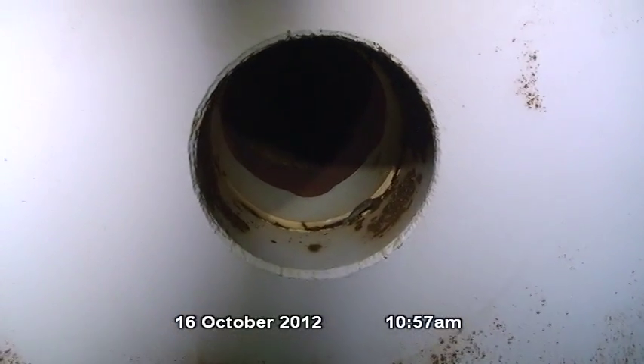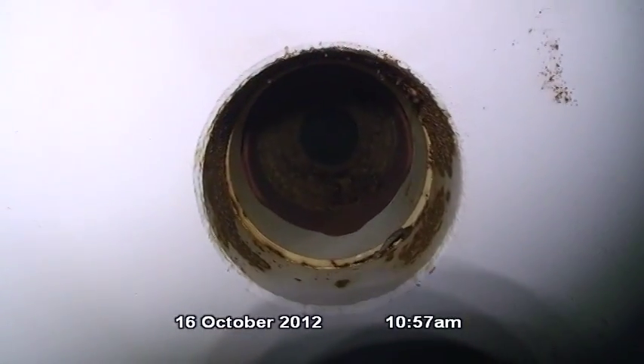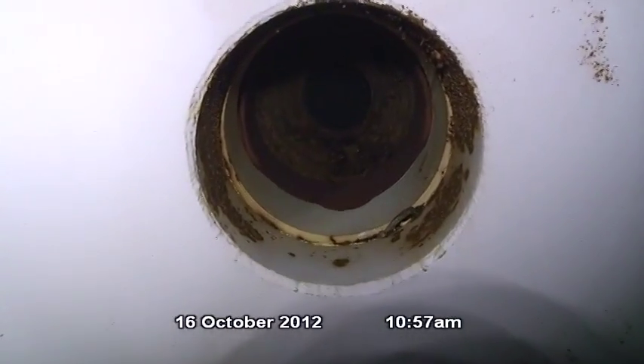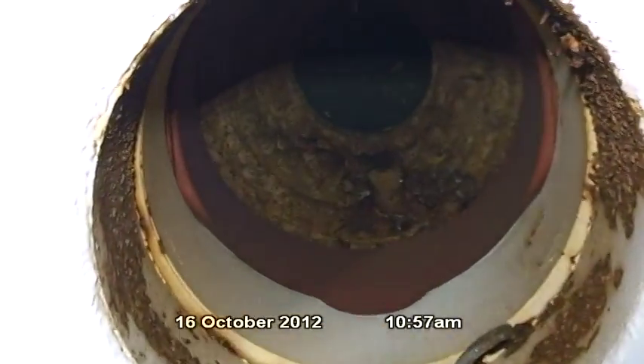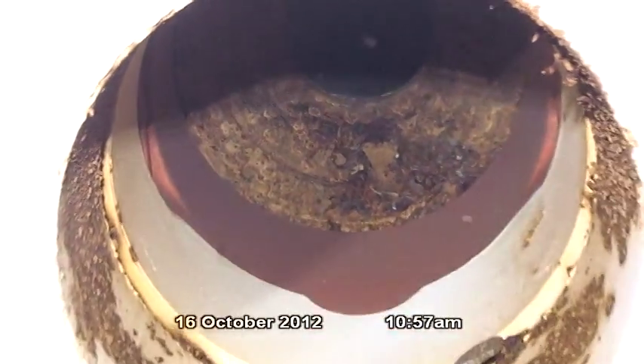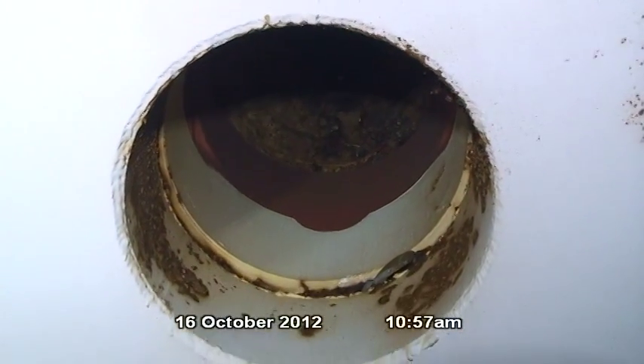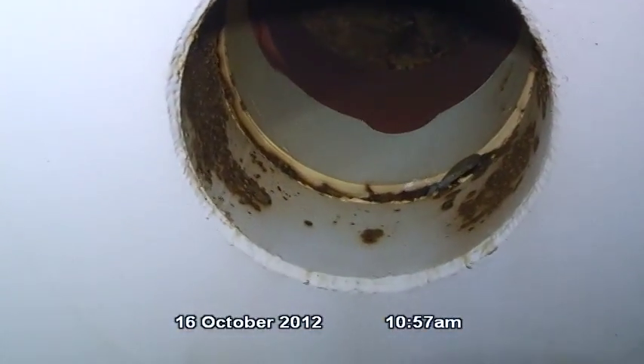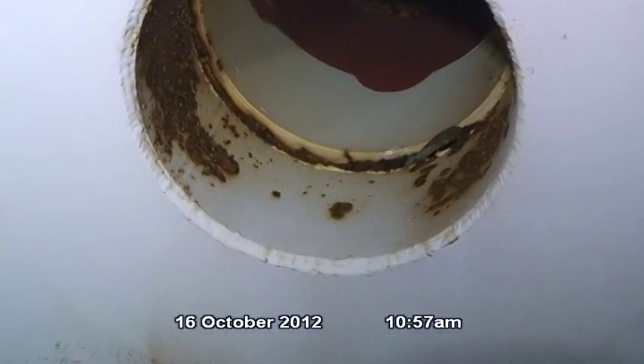Corrosion ranging from pinhole type to moderate corrosion is present in many locations on the lowest 4 feet of ring number 4. This is where the common line enters the facility through the shell. Light surface corrosion is present in many areas on the shell around the common line. The interior of the line is coated with epoxy. The majority of the epoxy coating on the interior of the line is in fair to poor condition. Moderate to dense corrosion is present in many areas. Obstructions are not present. The facility was not isolated for the wet inspection and cleaning.